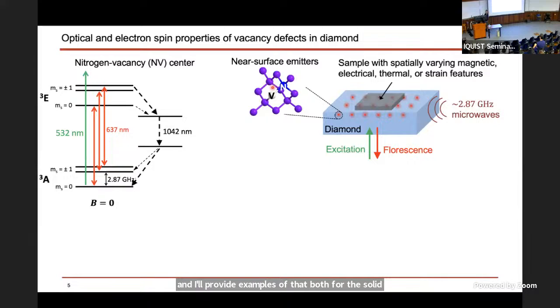Okay, so a quick introduction on vacancy defects in solid state crystals. In particular, probably the most popular one of which is the nitrogen vacancy center in diamond. What that consists of is, within the diamond lattice, you have a missing carbon atom, which we call the vacancy, and next to it a substitutional nitrogen. And this defect leads to a set of unpaired electrons that exhibit a ground state triplet state.